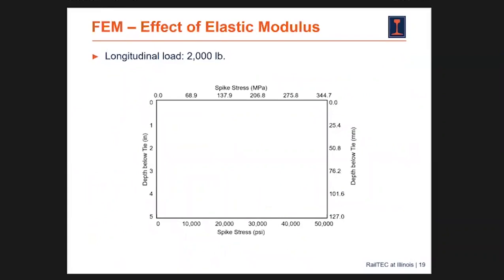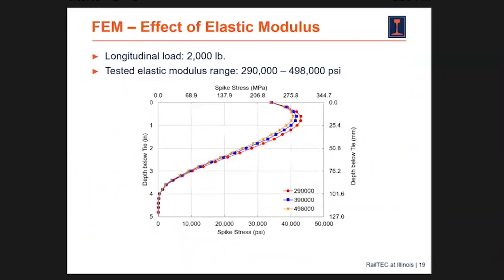Shushu then wanted to understand, what is the effect of this elastic modulus? Is there a benefit to changing a modulus? Should you target something softer or something more stiff? And we put in a compressive strength that would not crush. We made sure that it was very high and would not crush. And then we changed the modulus of elasticity values from the bottom end all the way up.